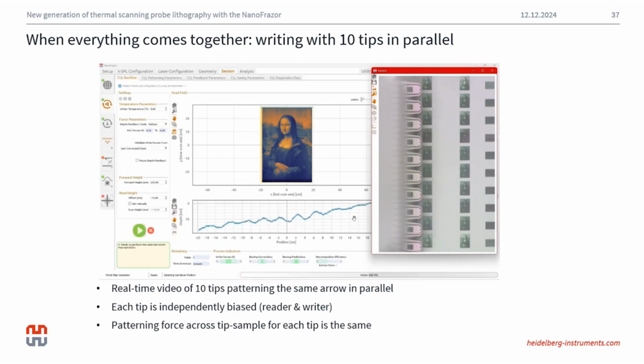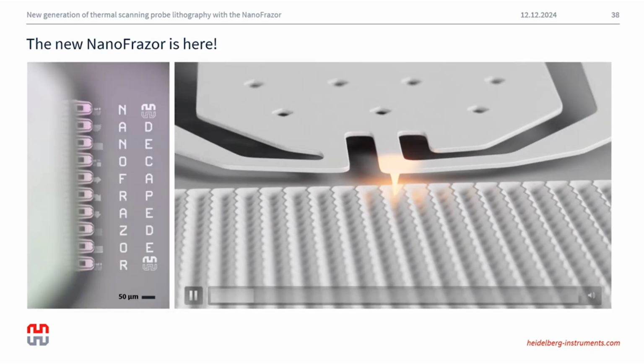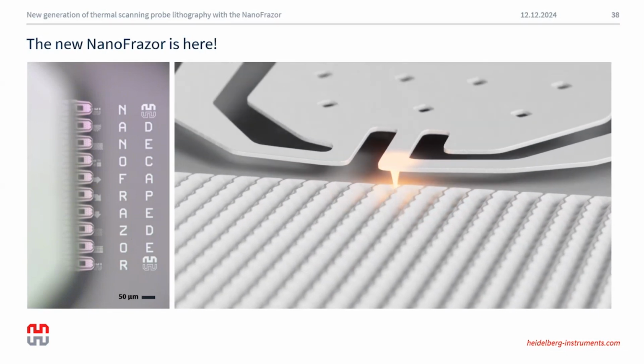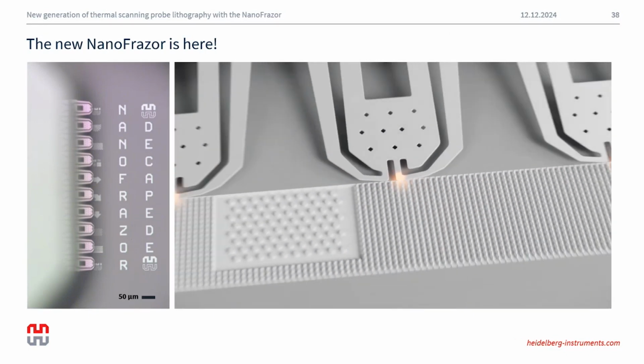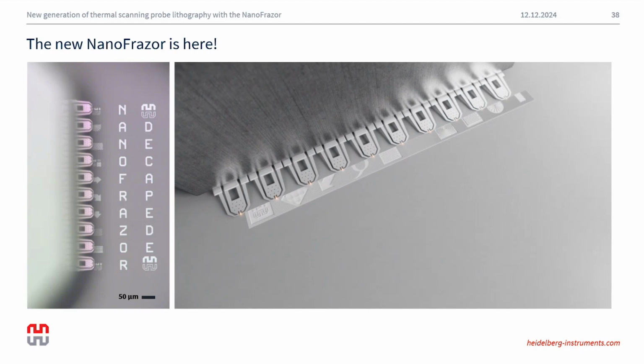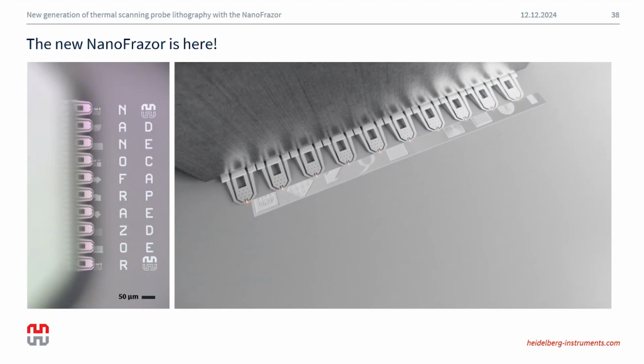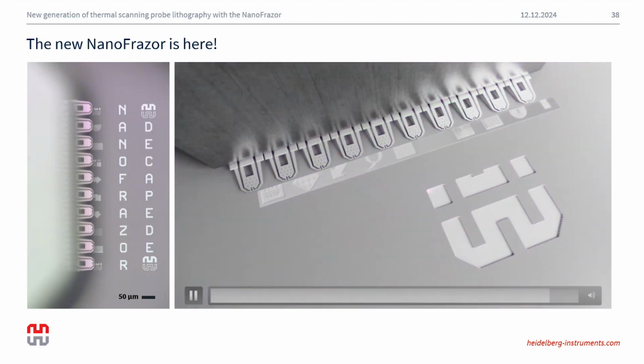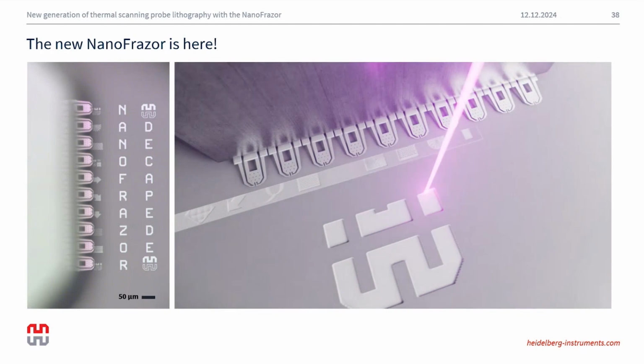There we go. So this was one of the first examples we've generated using the decapede with all 10 tips patterning the exact same grayscale image on a thick PPA resist. Of course, what we're working on at the moment is having each tip operate independently, and this can be to create grayscale features, 2D features, or both simultaneously. And these 10 tips can also be working in combination with the laser writer head, all within one system, and again, using the same material substrates.